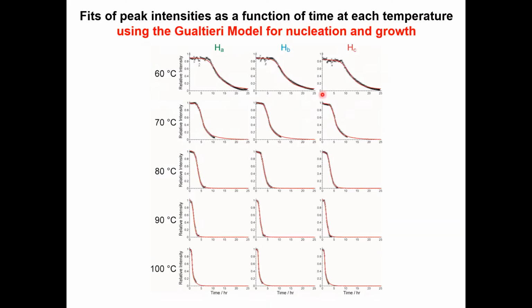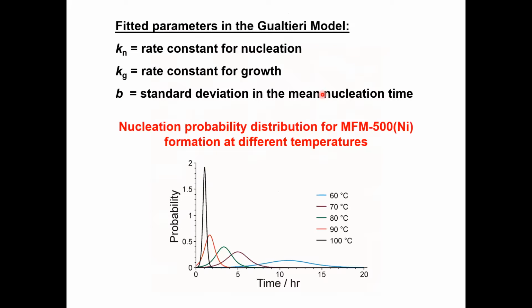As I said, very good quality fit as shown there, giving us detailed insight into the crystallization kinetics of the MOF material from in situ NMR data. So here we can see the nucleation probability at different temperatures from the Kn and the b parameters. Here we can see at high temperature, a very sharp and narrow window where nucleation occurs. At low temperature, a much broader, much longer period of time over which nucleation occurs.